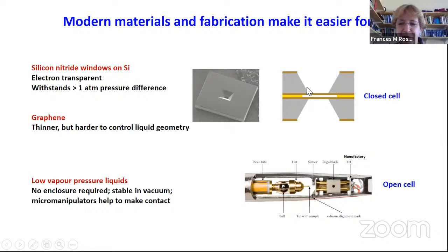So here's a cross-section of how you would make two of these chips into a closed cell by putting them face to face with a spacer layer between them. And the magic of silicon nitride is that you can develop it. It's amorphous, doesn't cause any contrast in the microscope. It can be very thin, a few tens of nanometers, and yet incredibly robust. It can stand atmosphere pressure differences across it without breaking. It's under tension, so it's kind of stretched flat, and it's just fabulous stuff.